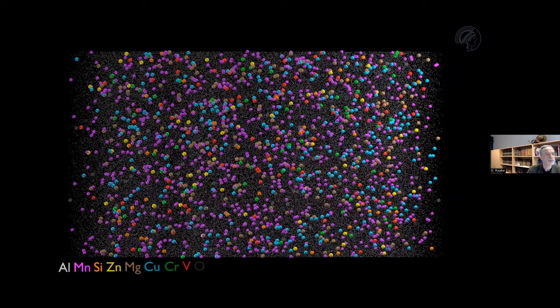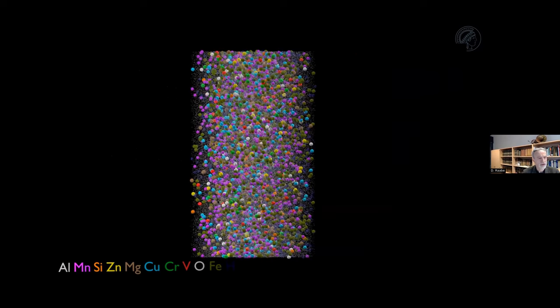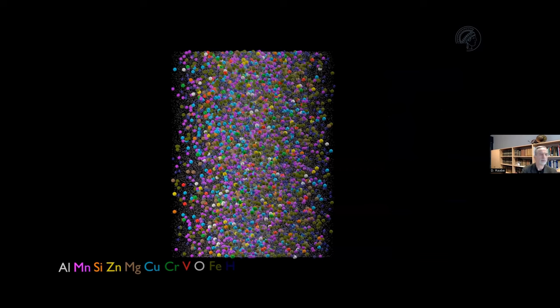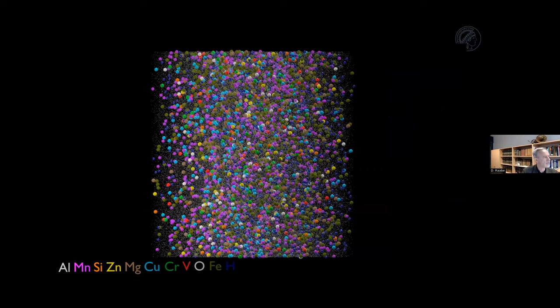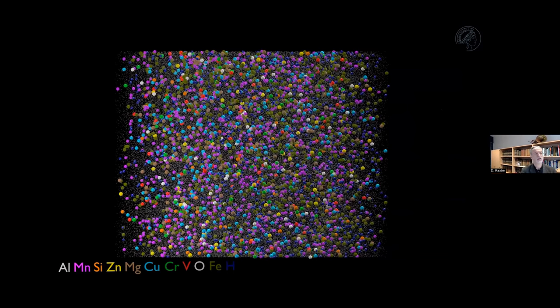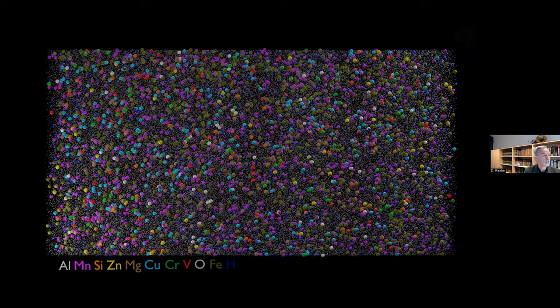So the second challenge is that the scrap is becoming incredibly dirty. It's becoming incredibly mixed, and you must blend these considerations in when you do thermodynamics and kinetics, that you are suddenly dealing with material development with 10, 15 elements, and must do the thermodynamics of such systems, which is very complicated. When you build a plane or a car, an ICE train or so, you must blend this in and must make predictions about the durability of such compounds.